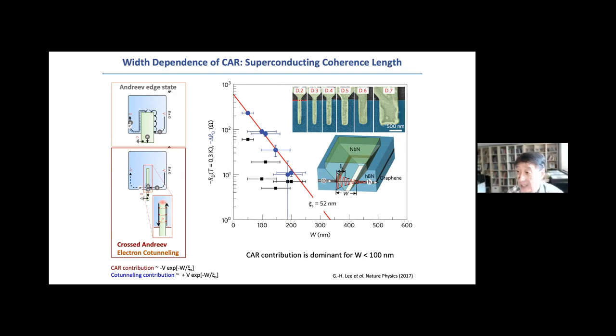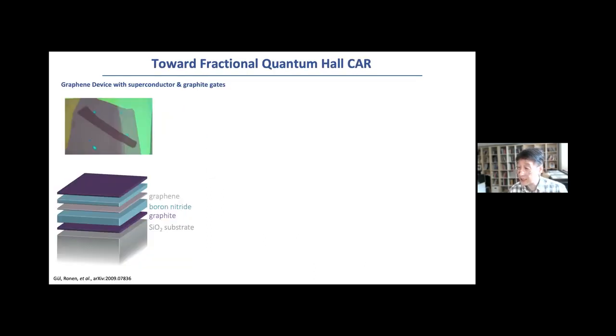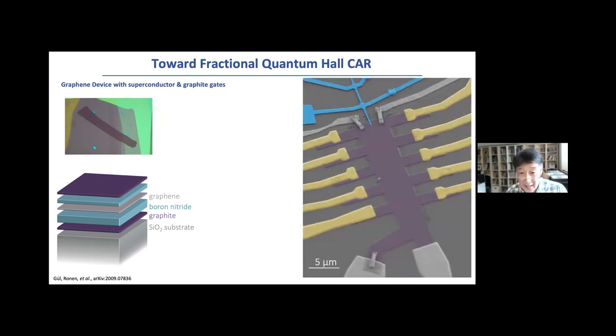edges seems to work. Now, the next level here is, can we actually push this into not only the integer quantum Hall, but the fractional quantum Hall effect? For that, we need to boost up our device fabrication even further. What we need is an extremely high quality graphene channel to realize this type of experiment. So we have to bring up this graphene encapsulated in boron nitride, and more critically, we have to put this top and bottom graphite gate, provide completely van der Waals stacks without any impurities, and then fabricate the devices out of it. It's challenging.